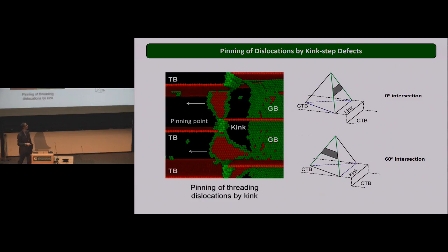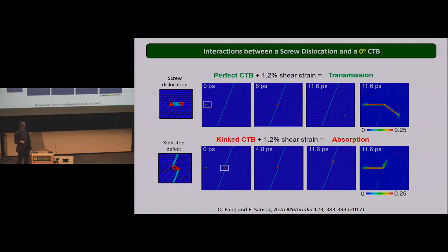More recently, with my student at University of Vermont, we've looked at the tiny details of the mechanics when you introduce a defect. In particular, when you have a dislocation intersecting a kink defect. In this category, you have two types: either the dislocation is directly along the kink, or it has a 60-degree angle, so it's called a 60-degree intersection. So we've used atomistic simulation to study that in detail. And this is just one example to show you how the defect can impact the mechanical behavior. We introduce a dislocation, a screw dislocation. You see the twin boundary is here, so we have two grains. And basically in the simulation, we force the dislocation to pass through the twin.